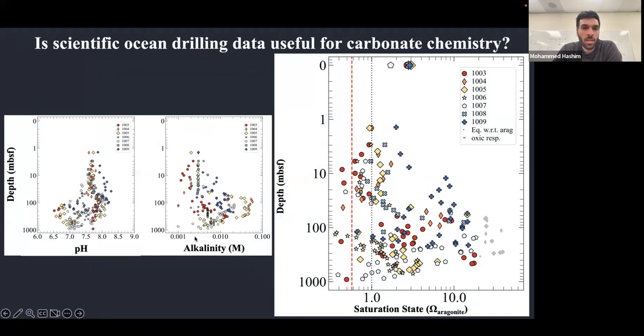So usually ocean drilling expeditions measure two properties, pH and alkalinity, and a bunch of other things. But for carbonate chemistry, you really need 2 out of 4 parameters to solve the whole system. And so that's what we decided to do. We took these measurements, we corrected alkalinity, we calculated carbonate alkalinity from total alkalinity, and we used the Pitzer ion interaction approach. I'm happy to talk about what that is and why it's important. But we calculate the saturation state in pore fluids.